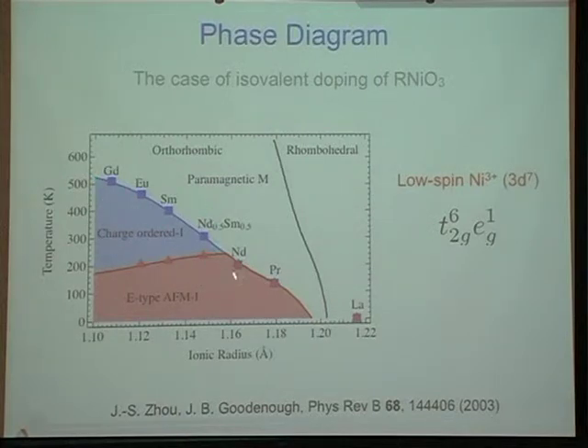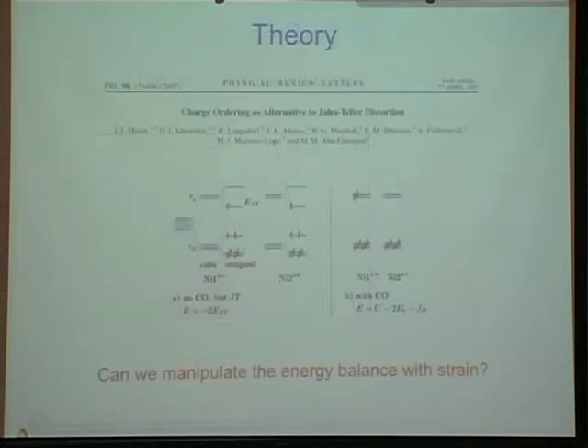And that metal-insulator transition coexists with an antiferromagnetic transition at a higher ionic radius, and then as you go smaller, they start to split apart. And I should also point out that the symmetry lowers again here, so it goes from orthorhombic to monoclinic.